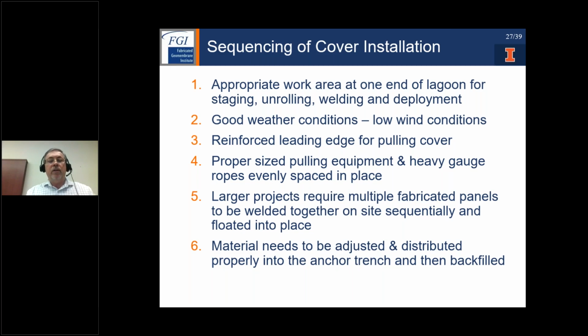So in terms of the sequencing of the cover installation, we follow a couple of really kind of broad steps. First and foremost, working with prefabricated panels, we need to have an appropriate work area or laydown area on one end of the lagoon. And this is where we basically do our staging, unrolling, welding, and deployment of the prefabricated panels. And we need a dry, well-compacted area with adequate space. Second, we need good weather conditions. We really have to make sure we have a low wind event day or a couple days when we're pulling these covers over. And of course, we don't want to see a lot of rain or moisture while we're installing these.